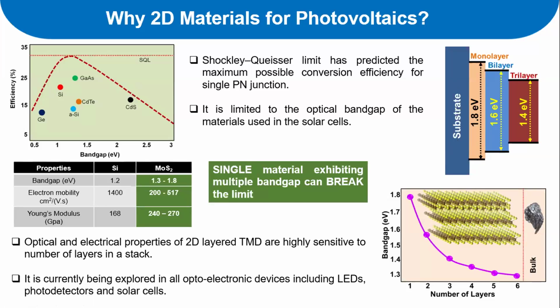If you consider a 2D layered semiconductor, particularly a material called molybdenum disulfide, then its optical band gap is variable, from 1.8 or 1.9 electron volt to 1.3 electron volt. And in this particular case, the material's physical characteristics also vary. It means if it is a direct band gap, then it shows 1.8 electron volt. If it is indirect, then it goes to 1.3 electron volt. So that is also possible to change.